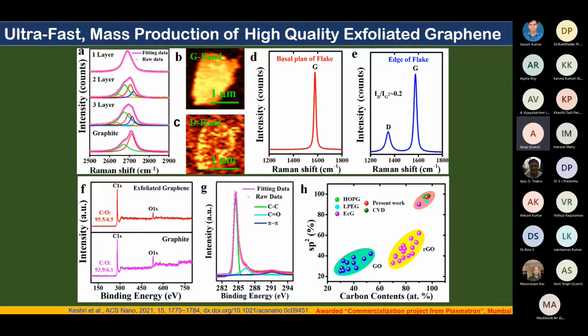Now, having dealt with the quality of our graphene, we did the XPS analysis, which you can see at the bottom. You can see the series of the low scan images and F, G, and H. In G, you can see the presence of the C-C bond, C=O bond, and the pi-pi bond. Using this, integrated over the area, we calculated the carbon by oxygen ratio.